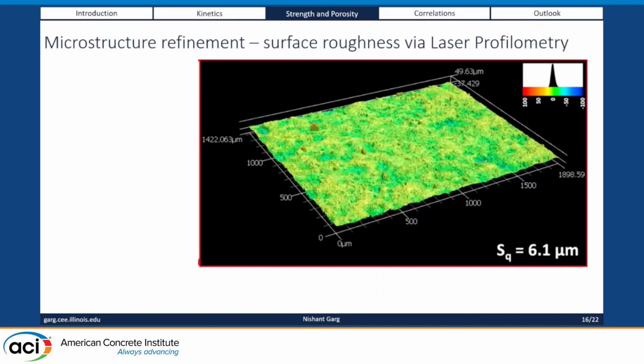Then the other thing we have been exploring is another technique to look at microstructure refinement, right? So this is laser profilometry. And some of these newer profilometers are pretty good. The resolution you can get on these systems is on the order of nanometers, and you can build a very detailed 3D map of the surface. And what we have found is that the surface maps, if it's large enough, done properly, can actually correlate to the porosity of a system.